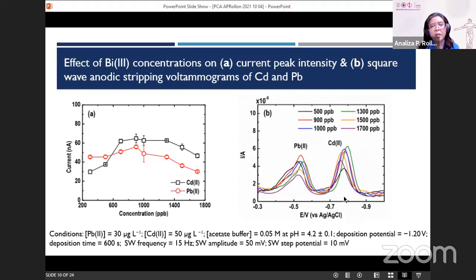This is for the lead and for the cadmium, and these are at different concentrations of the bismuth 3. Plotted against the bismuth concentration is the current peak intensity. And we can see here that near this area seems to be the maximum current intensity for lead and cadmium. By the way, we use a higher concentration of cadmium compared to lead because cadmium has less affinity and therefore less diffusivity. So we increase a bit the cadmium concentration.